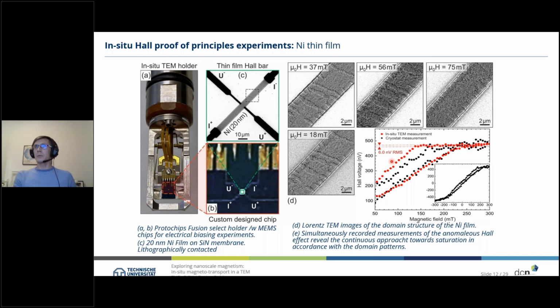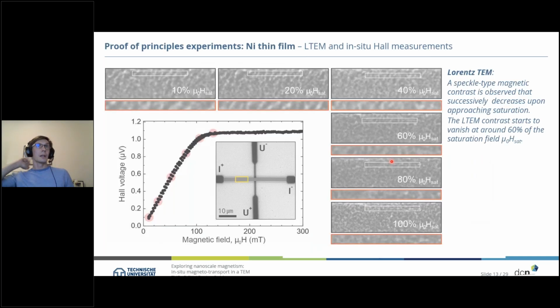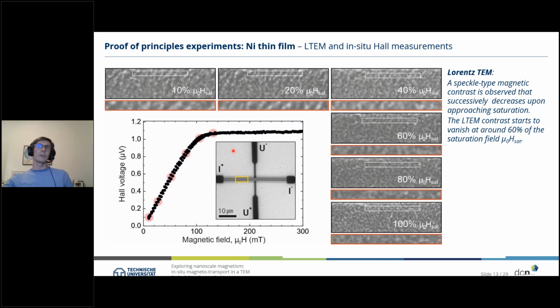But this was quite trivial, and we want to learn a bit more about our sample. We looked at the outer part of the nickel film, and we found some so-called speckle type of pattern, some magnetic contrast, which I plotted here in a higher resolution for different field values, now shown as percentage of the saturation magnetization, since this is easier to compare with simulation, which I will do on the next slide. So what we see in the zoom in is that this black and white pattern starts to vanish at roughly 60% of saturation, and then goes over to this standard finer pattern, which stems simply from the underlying silicon nitride window.